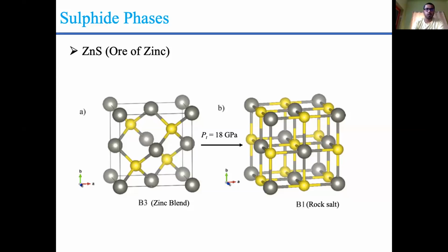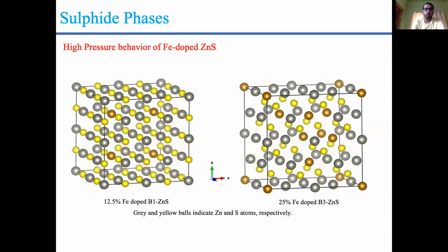I used the supercell approach for these simulations, and a substitutional defect mechanism while incorporating iron in the zinc sulfide structure. Here you can see the B1 and B3 phases, where the first is 12.5% Fe doped and the second is 25% iron doped. These iron positions are chosen so that the system has the minimum energy. Using these structures, I began my simulation.